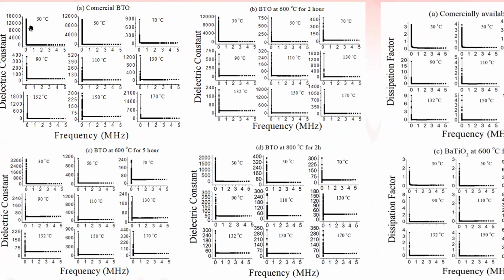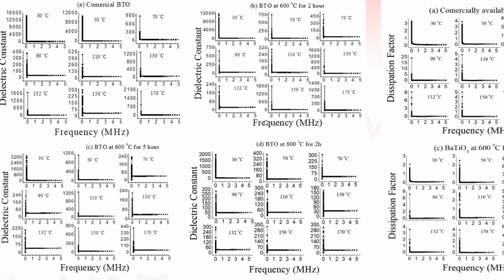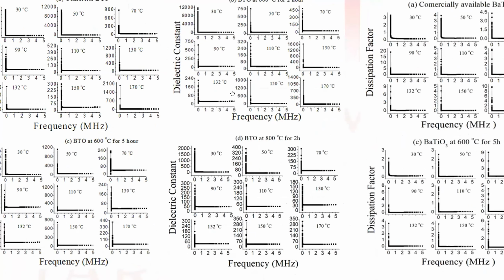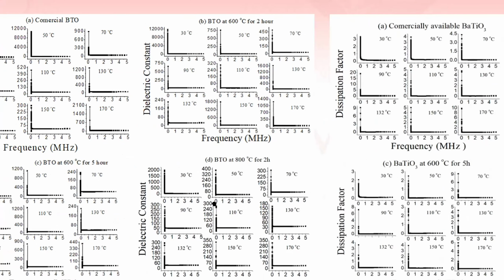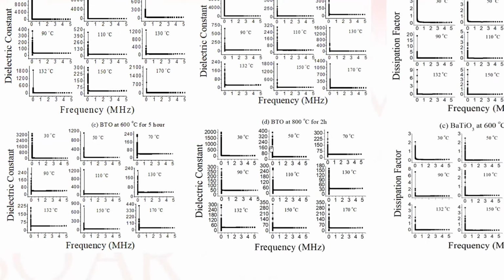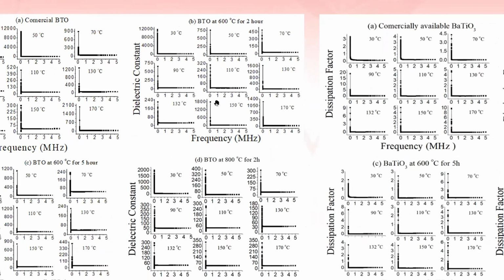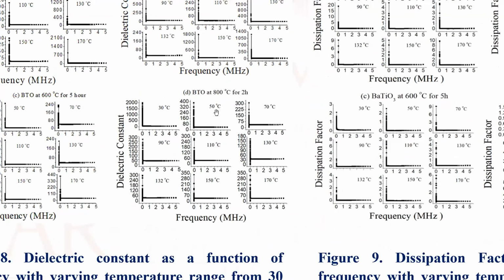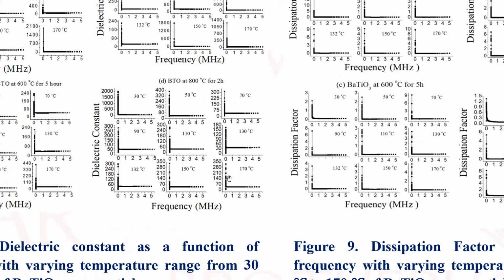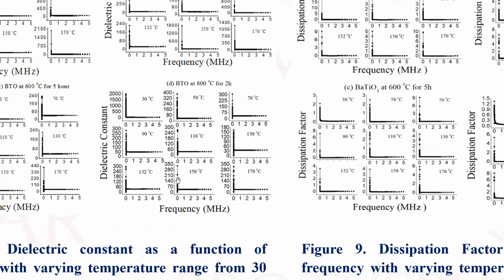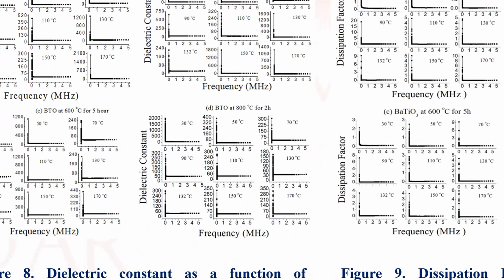As the temperature increases from 30 degrees centigrade to 170 degrees centigrade, the dielectric constant is prominently decreasing. And the same pattern we are observing in the synthesized nanoparticles. But the specific thing is that the nanoparticles calcined at 800 degrees centigrade for 2 hours give a low dielectric constant, which is very good, even at low frequency. And as we move further, the frequency increases.